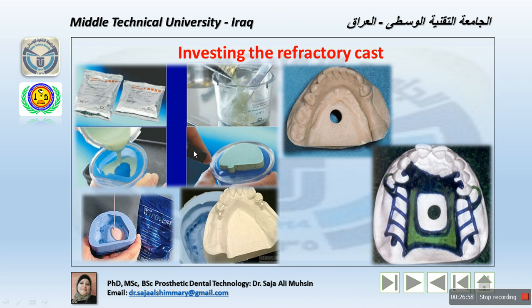Once set, remove the agar-agar mold from the flask, of course using an air jet. Look here, we are using an air jet after setting the material to make it easy to remove and not distort the refractory cast. Remove the agar-agar mold from the flask, taking care not to damage the model. Then section the agar and remove the sections. The investment cast should not be rinsed or trimmed with a cast trimmer, because this will cause slurry of the investment material to splash over the cast, which may not be entirely removed by rinsing, so it affects the accuracy of the cast.